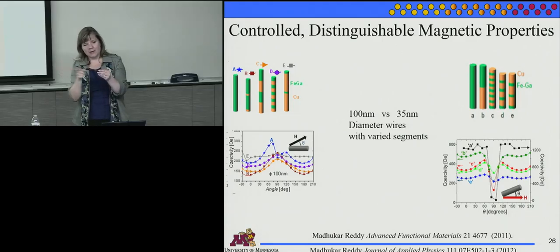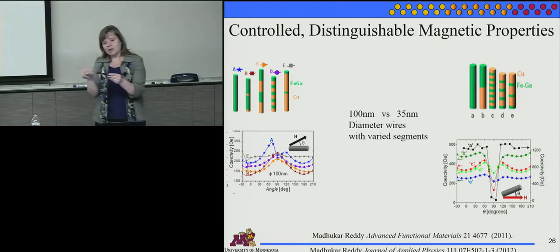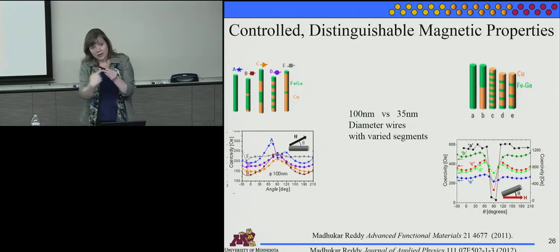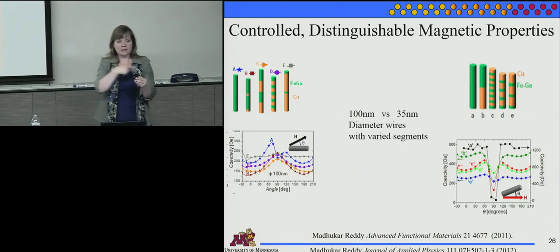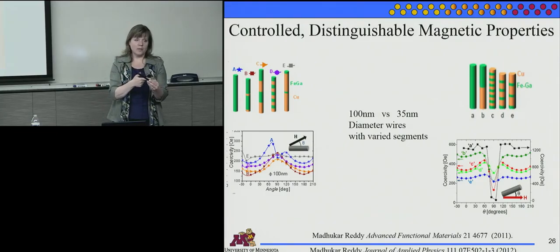So we basically are getting a minimum at 0 and 180 because it's a lower energy state if the moments are lined up like this and they can rotate around like dominoes. You have a wall that travels through. It could be that all the moments are lined up and they curl around and switch together. We can't really tell the difference between those. But essentially there's probably a vortex wall moving through these.